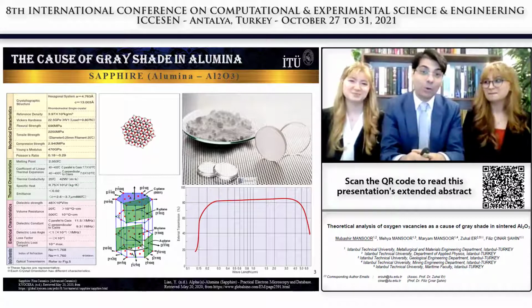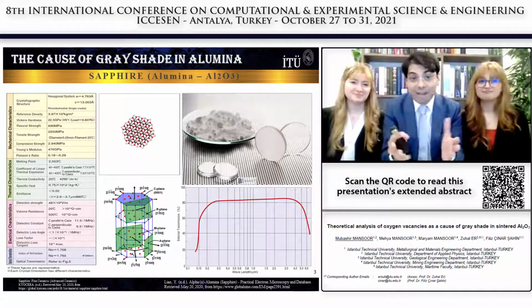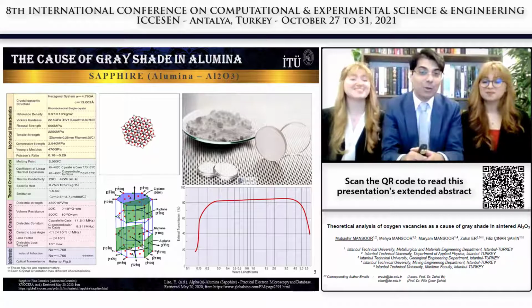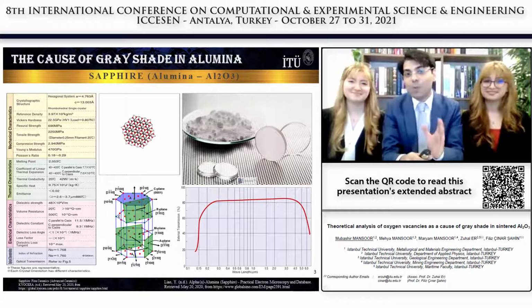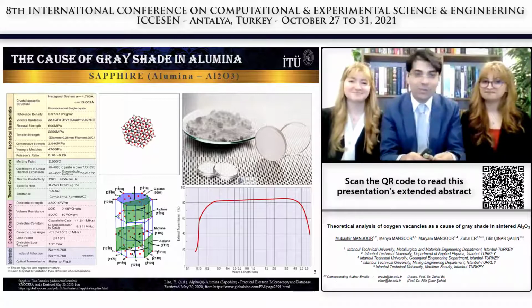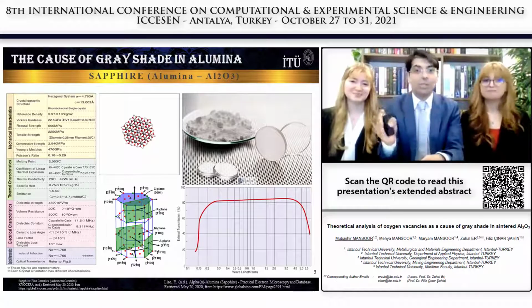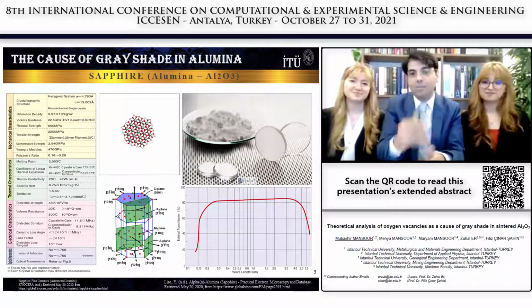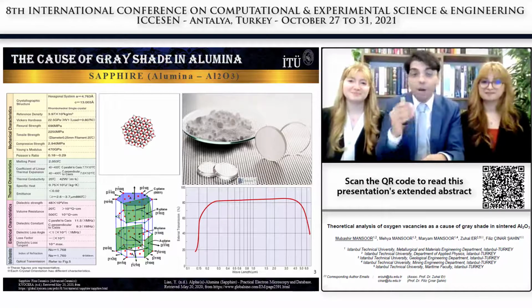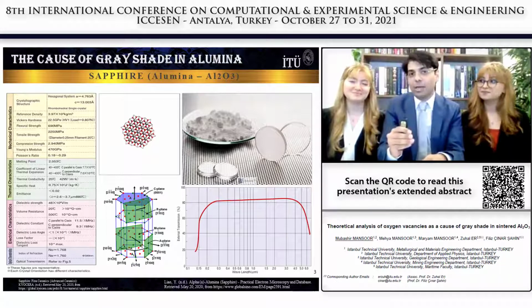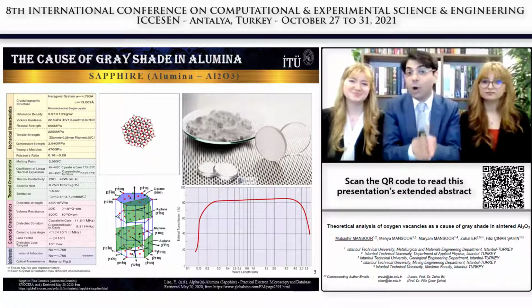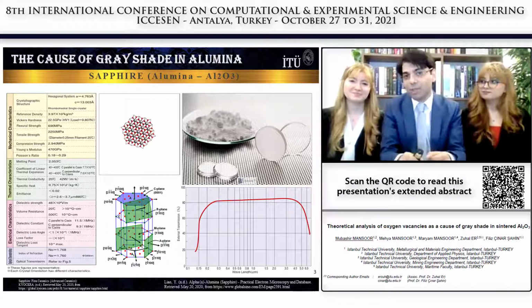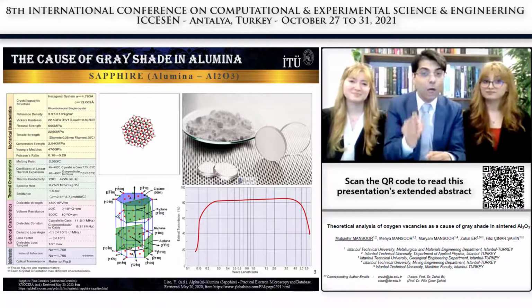So let's begin with a quick overview of the amazing properties of aluminum oxide. The single crystal form of alumina is a very well-known material, sapphire. It has been used as a gemstone for perhaps millennia. But this is so much more than a gemstone. The amazing hardness of 22 gigapascals, melting temperature of 2050 Celsius, resistance to many corrosive media, wide transparency range from 200 to 4,000 nanometers makes it an amazing material for all sorts of demanding applications. However, producing single crystal alumina or sapphire is not an easy task. So an alternative which can provide almost all the industrial benefits of sapphire is actually polycrystalline transparent alumina ceramics.